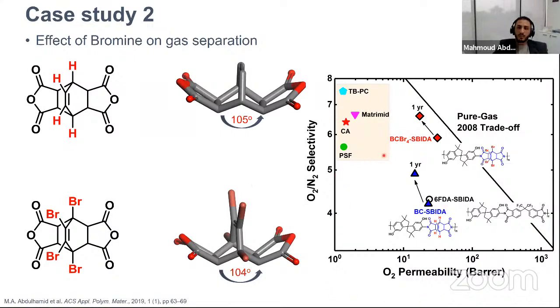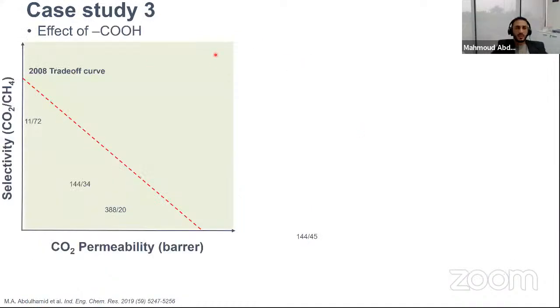So we decided to look into more polar groups. We wanted to see what is the effect of COOH on performance. So we first checked the literature to see if there are any PIM materials prepared with COOH groups. We haven't found any polyimides consisting of a porous polymer and having a carboxyl group. But we found a very common polymer that everyone in academia is trying to use because it produces very good selectivity of carbon dioxide over methane. So this is performing in this region, where we have a carbon dioxide permeability of 11 and a selectivity of 72.